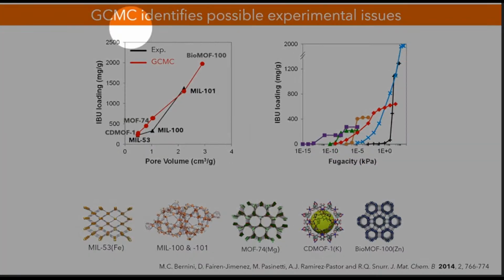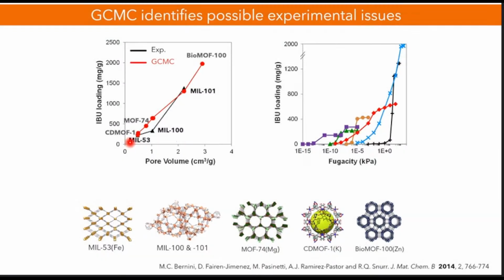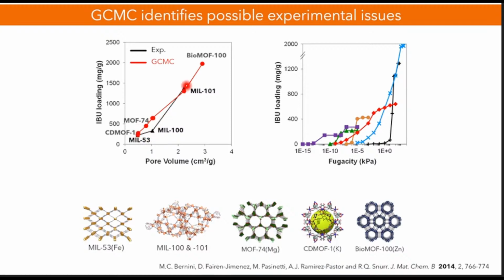So basically, this comparison is represented here on the left of the slide. This is the loading of ibuprofen per gram of metal organic framework material, and this is the pore volume. In the simulations, you can see we have a very nice correlation between the pore volume and the loading, which makes sense. Then we compared with experimental data available in the literature for MIL-53, MIL-100, and MIL-101. We have a really good match here, and an over-prediction here, but the experimental data is the one that looks too low.